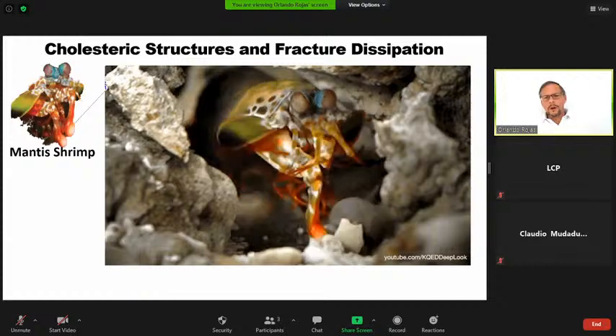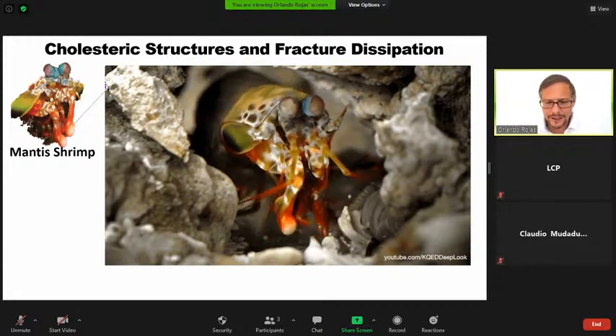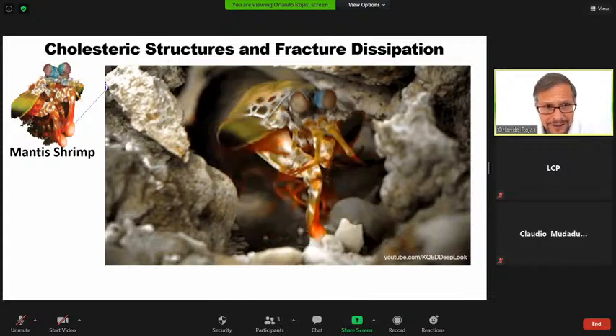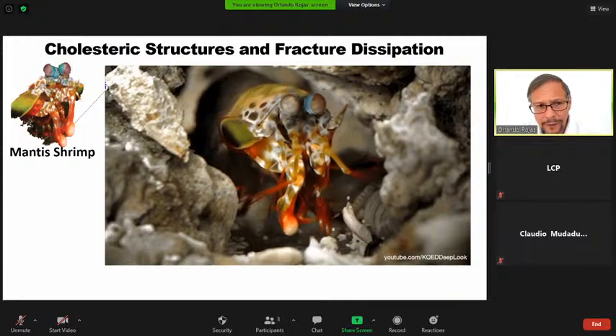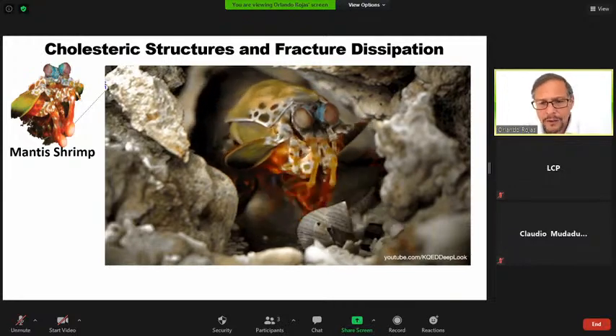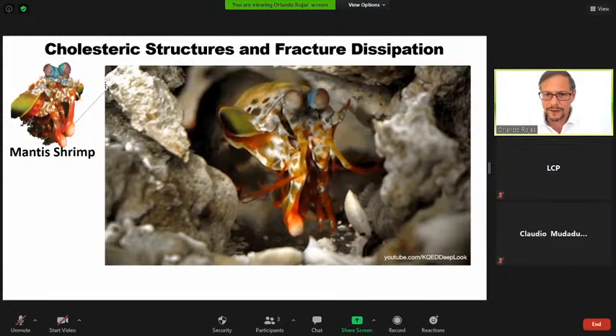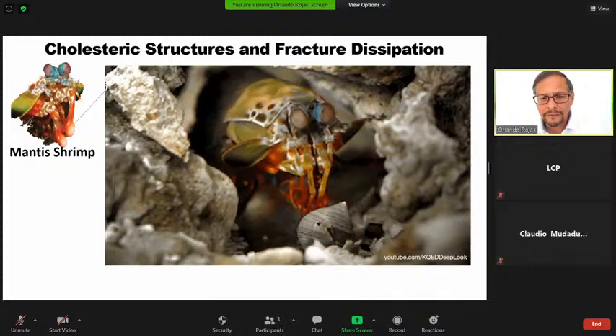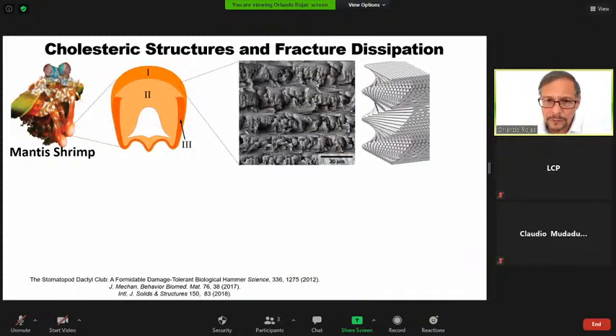And that's shown here in these slides that I have no time to explain, but you can go to the reference and check the beautiful work that shows again cell proliferation and how the nanocellulose becomes a scaffold for bone growth. The other one also in the group that is interesting is the idea of using very lightweight materials, aerogels again, mimicking the case of the hammer, if we can call it that way, of the mantis shrimp. So the mantis shrimp is this sea animal that is very strong in this little hammer that it has at the end. And the reason for that strength has to do with something that we have reviewed earlier, and is the assembling of the nanomaterials in the biological system.